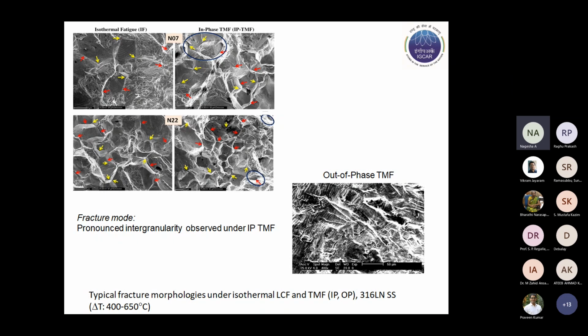So the important thing is, even though the average temperature is much lower in the case of TMF, significant creep damage accumulation occurs. One reason for this could be that in the isothermal case, the damage that happens in the maximum tensile part, some of it gets reversed during the compressive part of the cycling.